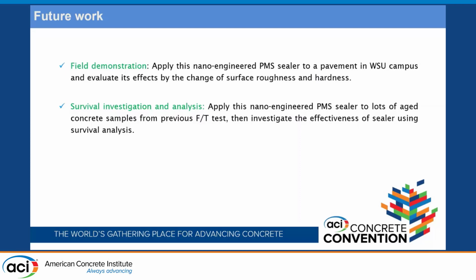Okay, got it. Thanks. Actually, if I may clarify, this is a penetrating sealer. Like many of the other penetrating sealers, they have to go down, so they're not staying on the surface, even though there's a little bit of film. So mostly it's going down. Most silane and siloxanes for bridge decks come out every 3 years. Usually you have to redo it because of the traffic operation. This one, we don't know for sure, but it should be as good as cementitious. And another unintended benefit is this one is pretty low in volatile organic compounds because it's water-based, so there's no solvent.